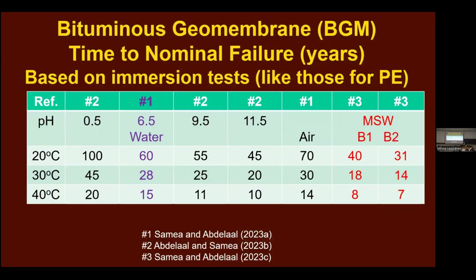And let's just look at it. It's got a nominal failure time of 45 years for solution 2, which is highly acidic, 0.5, 28 years in water. So it actually prefers the acid. 25 years at pH 9.5 and 20 years at 11.5. In air, it's 30 years. In municipal solid waste leachate, one is 18 years and the other is 14 years.